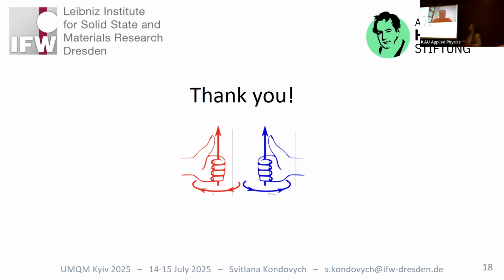That's why the chiral symmetry breaking occurs. However, the symmetry of our domain wall does not allow this kind of chiral effect. So you have parity of the magnetization components, so the chiral magnetostatic effects do not appear. So in our case, the similar chiral symmetry breaking as observed by Hertel is generated by the DMI.